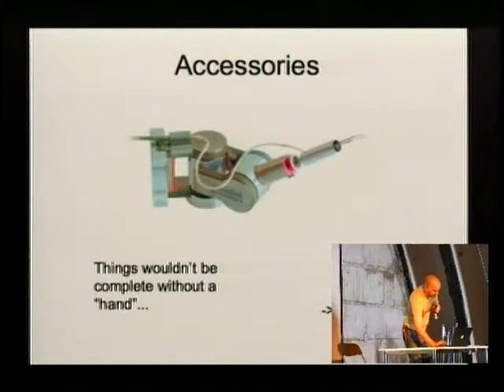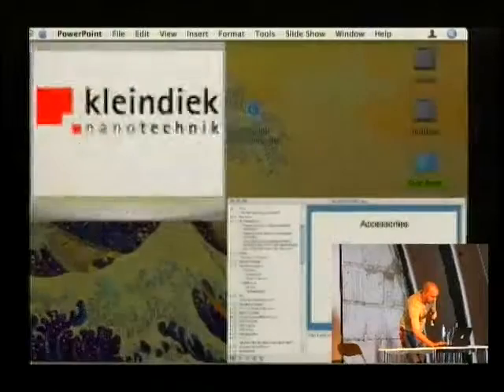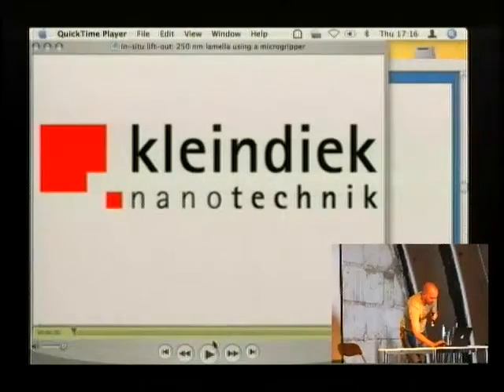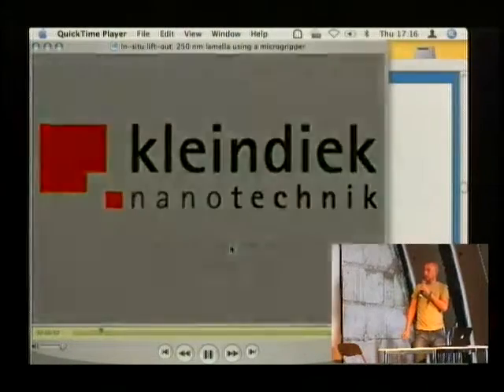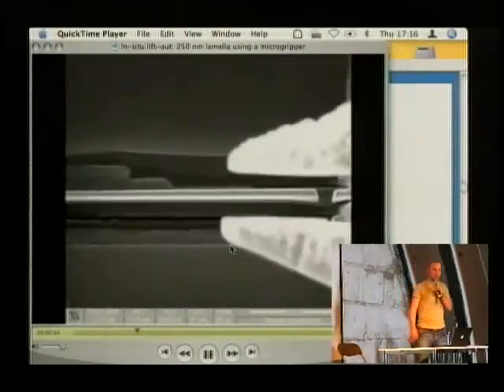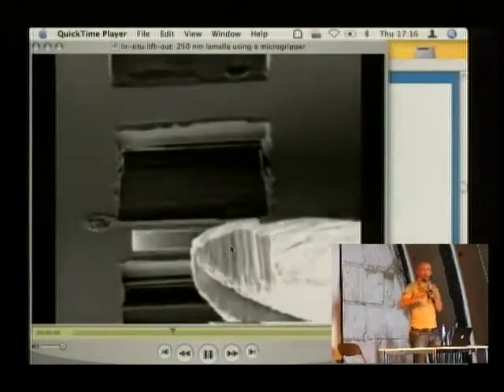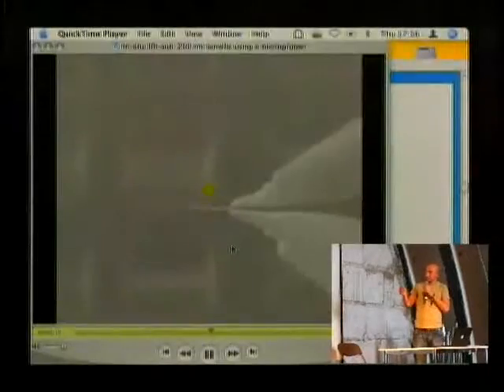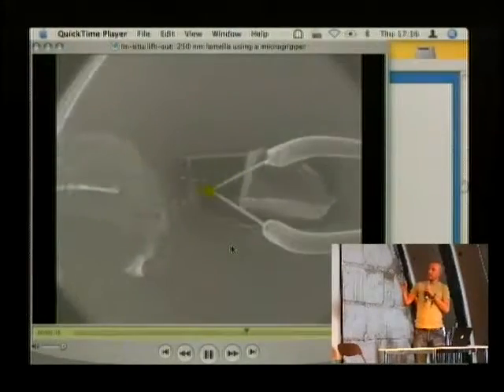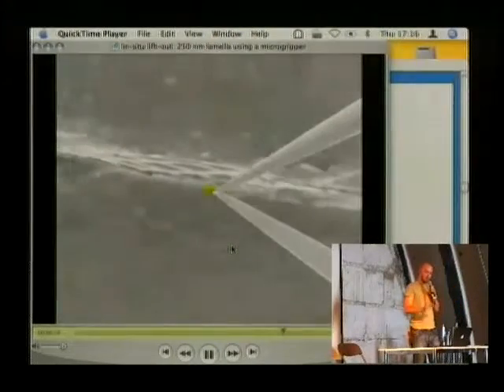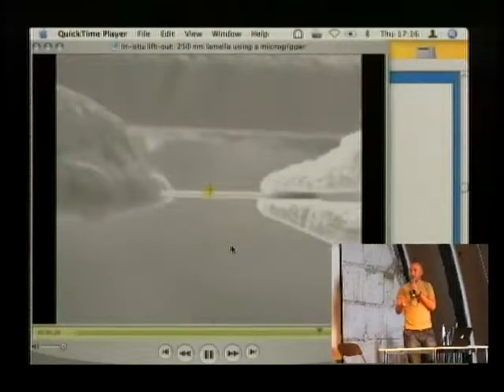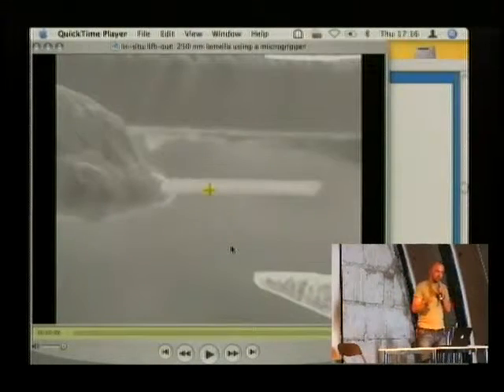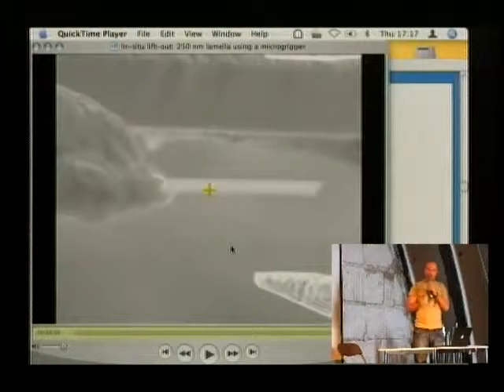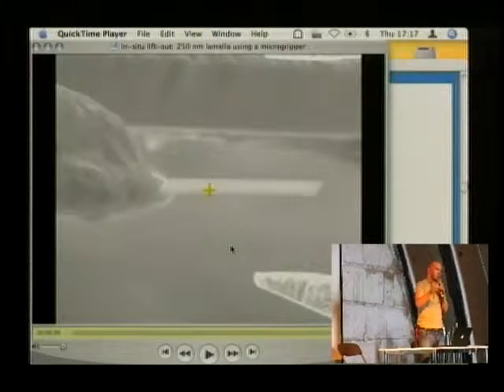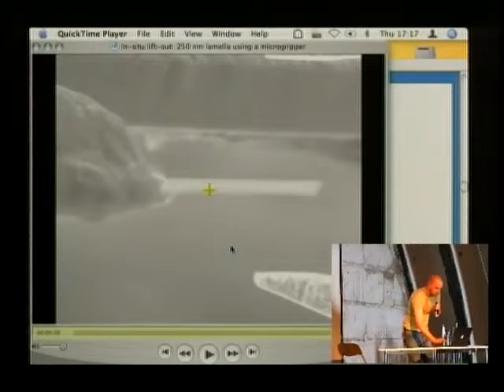Things wouldn't be complete without the hand. So I have this little video that maybe works. Typically in these systems you also have some sort of micro or nano manipulator. Here is a demonstration by Kleindiek. They built these grippers that can pick up nanometer-sized objects. You can transport them within the FIB. You can use the focused ion beam to cut off pieces of interest, take the gripper, move them around, weld them to other surfaces. So this is a pretty powerful tool.